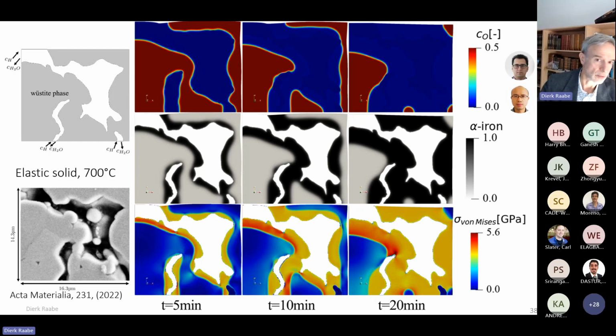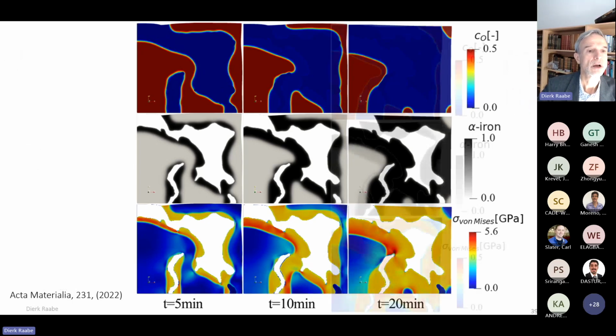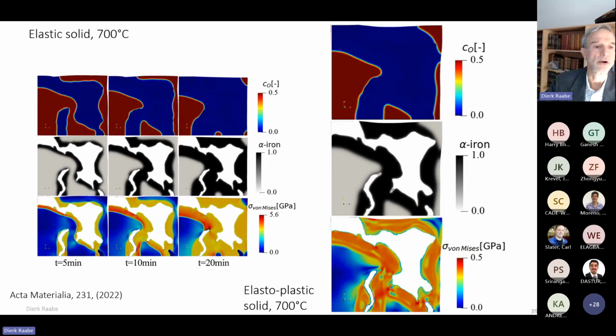And you can see here with more than 5 gigapascal locally, these stresses are of course far too high. That's not realistic. So we have also changed our phase field calculation into an elastoplastic form so that we cap beyond a certain elastic stress the response into inelastic elastoplastic response, as you see here.